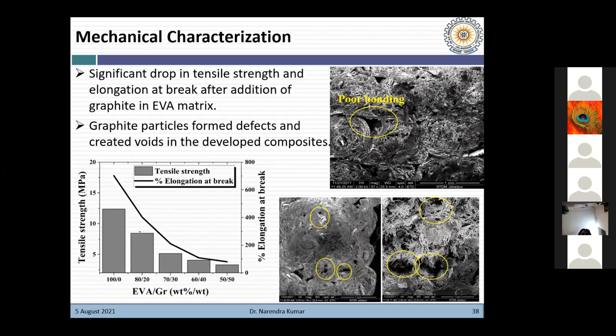So this is the result for tensile strength and elongation at break. Both were degraded when we added graphite particles into the EVA matrix.